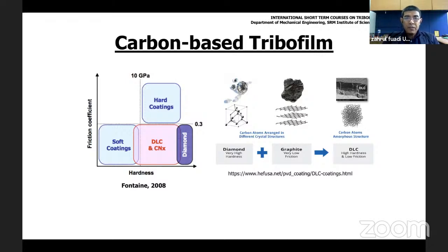This kind of principle can be achieved by using carbon materials like graphite or amorphous carbon, which is called diamond-like carbon coating. If you see this graph here with the DLC diamond-like carbon coating, it has a high hardness, but it will give a low friction.